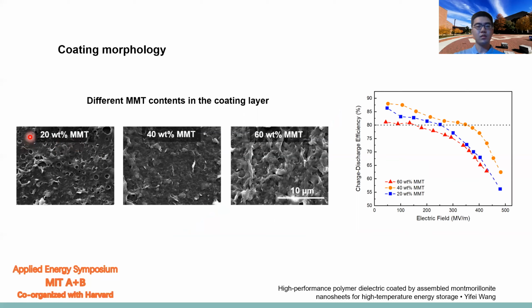If we introduce just 20% of MMT in the coating layer, we can find there are some voids on the surface. If we increase the MMT content a little bit, the surface becomes smoother. But if we further increase the MMT content, the surface roughness increases, so we find a rough surface instead of a smooth surface. After we check the efficiency of the coated polymers with different MMT content, it agrees well with the morphology. The samples with 40% MMT show the highest charge-discharge efficiency.